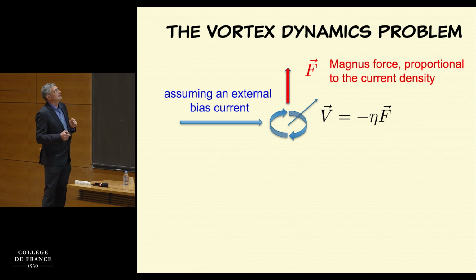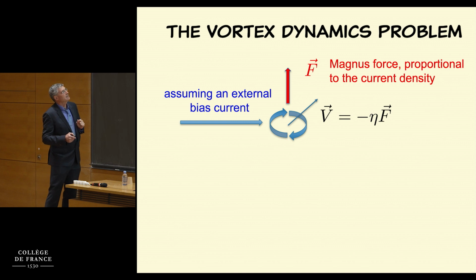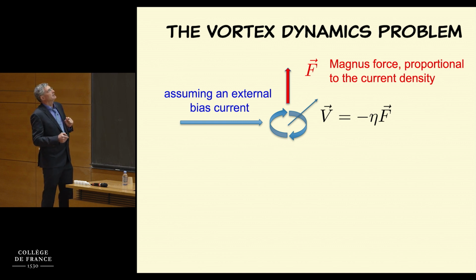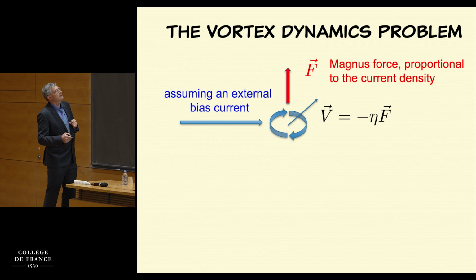Vortex dynamics says that one can think of vortices as subject to a force coming from an external bias current. So this expression here, well known from hydrodynamics, will tell you that if you put a bias current in a system and you have a vorticity, the vorticity will have a force on it wanting to move perpendicular to the current, but perhaps it won't move perpendicular. This depends on the tensor called viscosity tensor. So if you know the direction and the magnitude of the velocity introduced by the current, you can translate this to an electric field and solve the transport problem of current versus electric field. The problem is this eta.